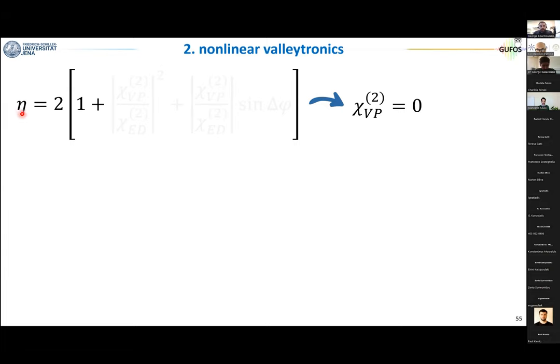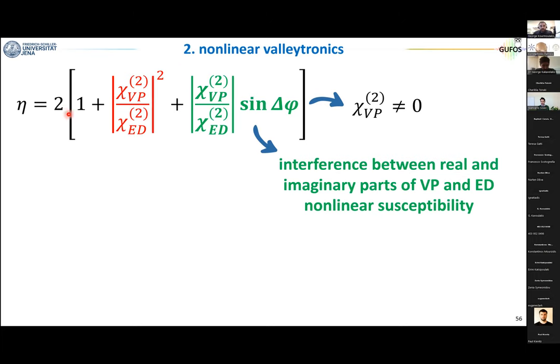Let me only tell you that if you calculate this ratio, assuming that there is never valley polarization, not even in the circular case, so time reversal symmetry is always preserved, then this ratio, circular to linear, should always be equal to 2. And this, let me tell you, is the assumption that everybody doing nonlinear optics in 2D materials has used until now. Now, if you consider that the circular polarization breaks time reversal symmetry and induces a valley polarization, the ratio will be very different from 2. And in particular, you can have an element that goes like the square of the ratio, valley to electric dipole, and something that goes linearly with the ratio plus an interference term. This interference term only arises and only comes into play if you consider that these elements are complex and you have a phase shift, so real and imaginary part, between electric dipole and valley polarization.